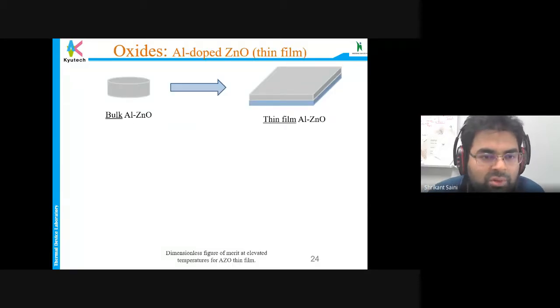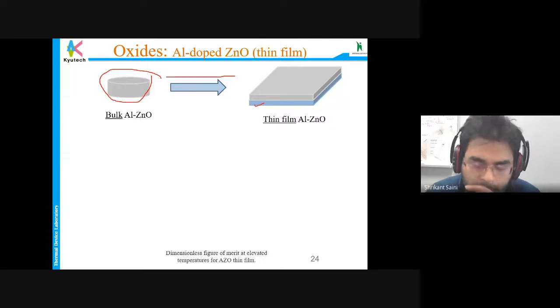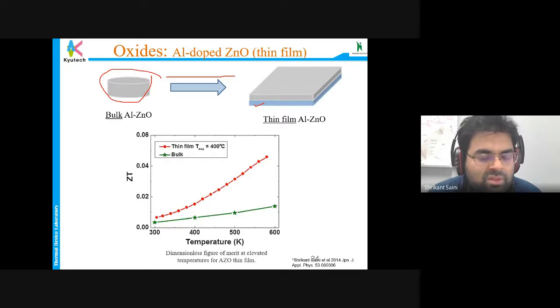So in the thin film case, what happens here is you have a bulk of the material and you transform this material into a thin film. This is the substrate and this is the film on top. When we deposit this material and look at the ZT, or the figure of merit, we found the ZT has almost 5 times enhancement over the bulk material, and that is another best reported result for an N-type thermoelectric material in the oxide case.